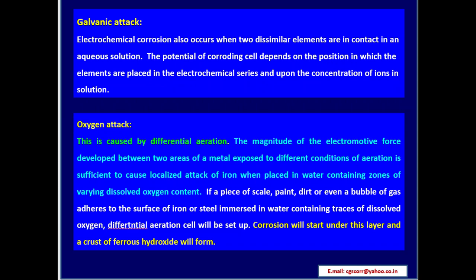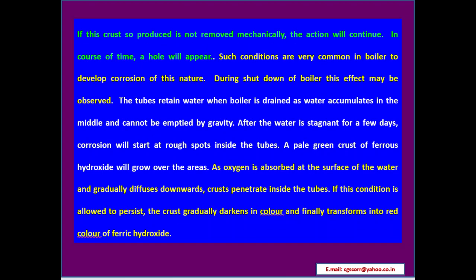If a piece of scale, paint, dirt, or even a bubble of gas adheres to the surface of the iron or steel immersed in water containing traces of dissolved oxygen, a differential aeration cell will be set up. Corrosion will start under this layer and a crust of ferrous hydroxide will form. If this crust so produced is not removed mechanically, the action will continue. In the course of time, a hole will appear. Such conditions are very common in boilers to develop corrosion of this nature.